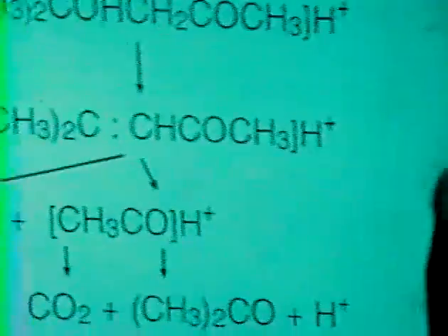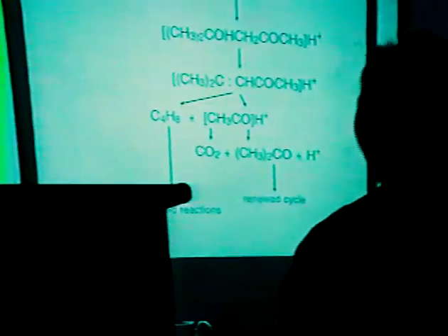We think that the acetone is first protonated with this hydrogen of the structural OH groups, and this protonated acetone reacts with acetone to diacetone alcohol, and after the dehydration, mesityl oxide. These reactions are well known from homogeneous organic acid-catalyzed reactions, and all these steps were also found on the surface using infrared measurements and carbon-13 MAS NMR.